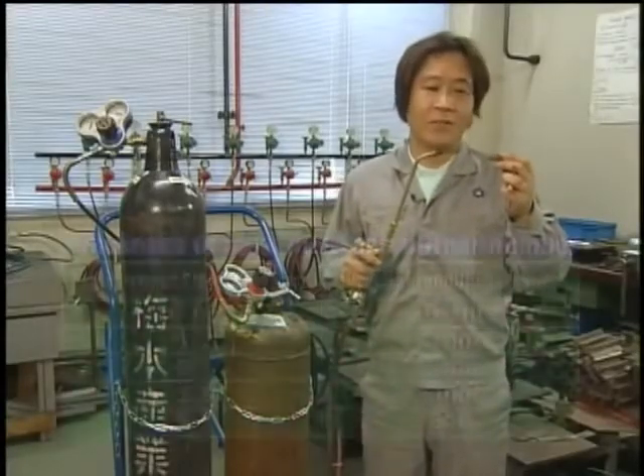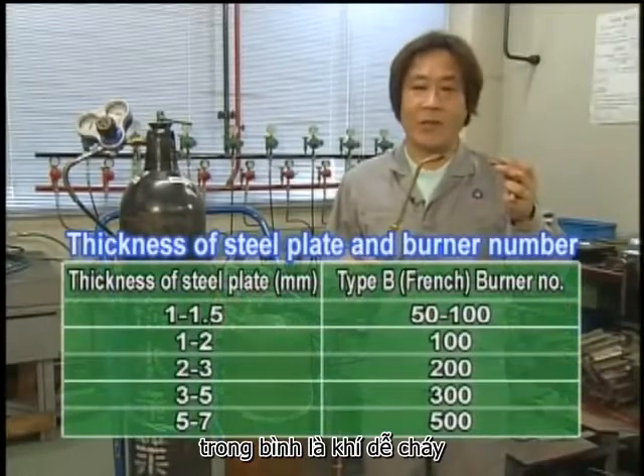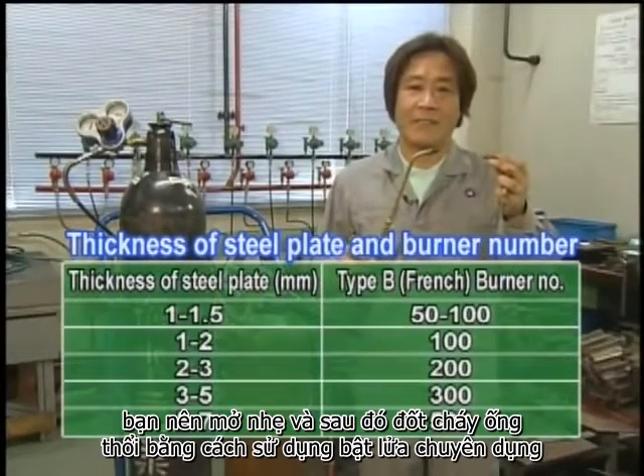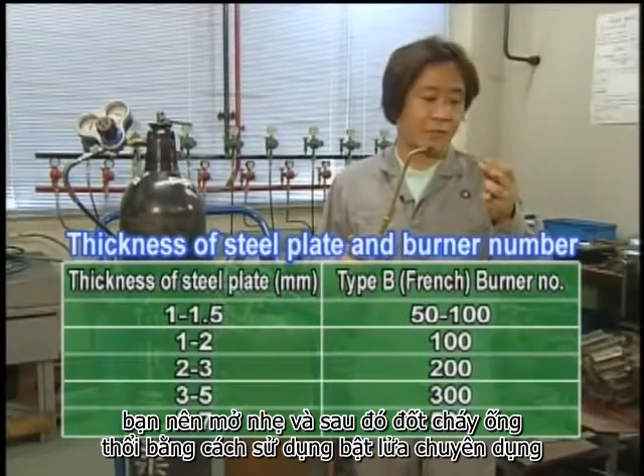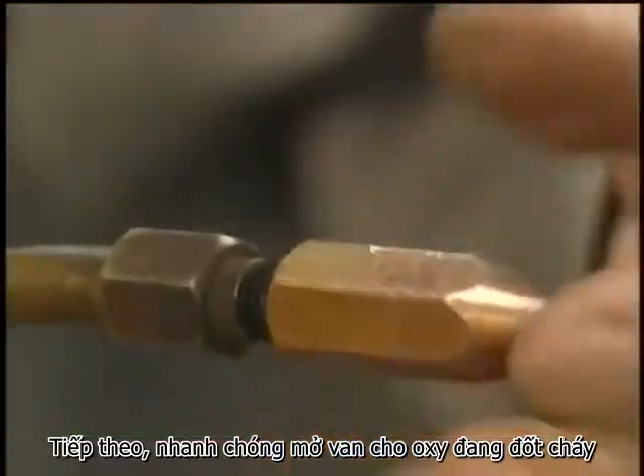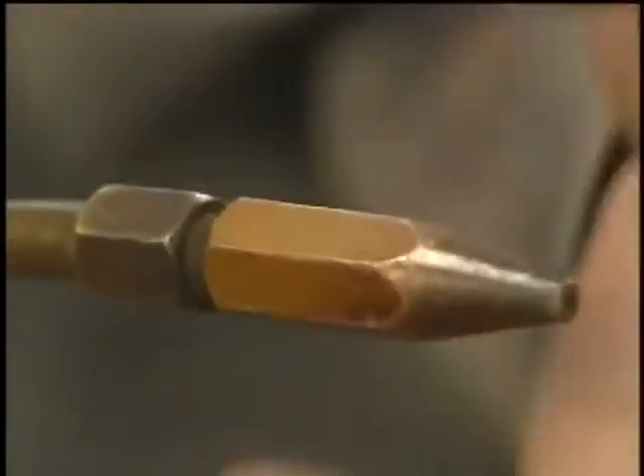Attach the nozzle to the blowpipe. Different nozzles are used according to the thickness of the material to be welded. In this case, the material is a 2 mm mild steel plate, so a number 200 nozzle is used.